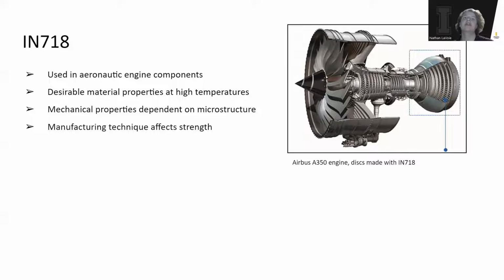The method used to manufacture Inconel 718 also changes its mechanical properties. Rolled manufacturing is when a metal is rolled into strips. The process of thinning the metal into strips causes a unique grain pattern, forming a high tensile yet brittle structure. Selective laser melting is an additive manufacturing process that uses a bed of powder and a highly precise heat source to fuse the powder together. This printing process results in a material with increased tensile strength and ductility.